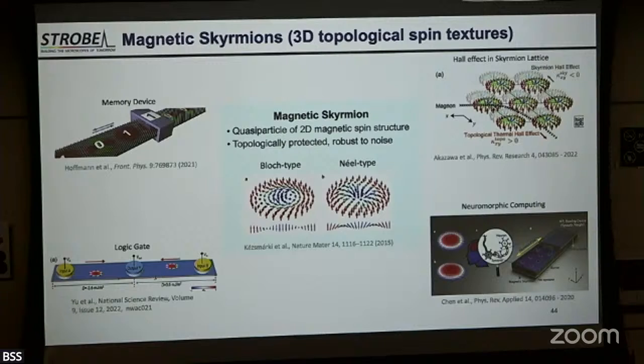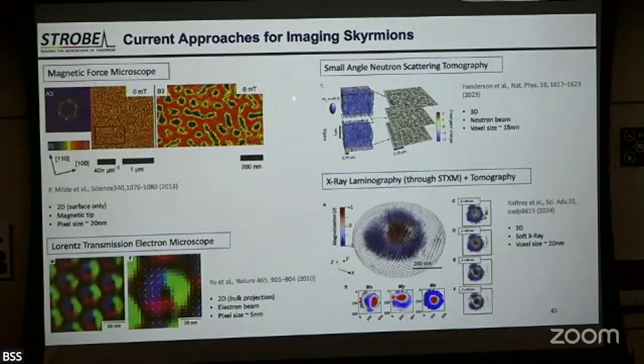And so people look at these skyrmions with magnetic force microscopy or small angle neutron scattering or Lorentz transmission electron microscopy, or Peter Fischer has looked at a single skyrmion and then milled out the single skyrmion disk and then imaged it at the Advanced Light Source. It would be wonderful if we had a way of imaging the full 3D dynamic spin texture. We're not anywhere near being able to do that, but we started with trying to make a general way of imaging a 3D spin texture. Most of these are not compatible with good time resolution, or they don't have 3D capabilities.